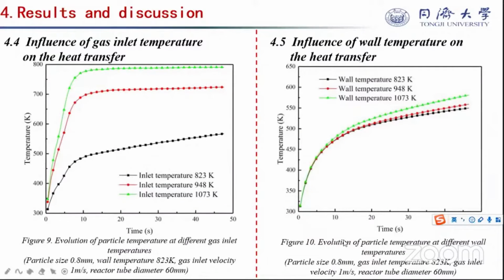The evolution of particle temperature at different wall temperatures is shown in Figure 10. As we can see, in the initial time, the temperature rise speeds are almost the same under different conditions. This is because in the initial time, the temperature difference between the flue gas and the particle is huge.